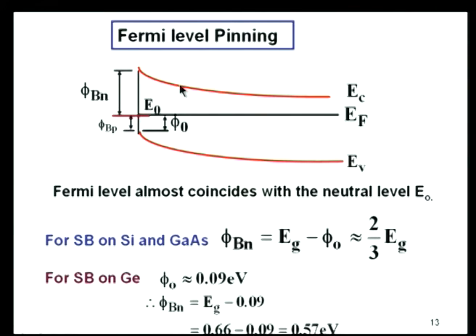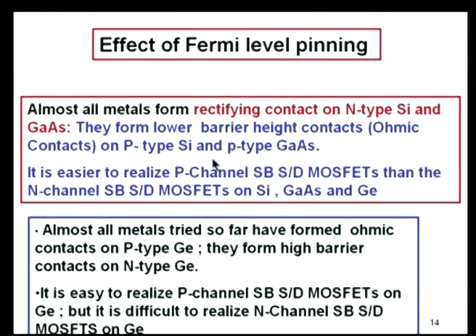So, rectifying: whenever you put a metal on these semiconductors, it will make a rectifying contact. So, it is very easy to make Schottky barrier diodes on n type materials, and it is very difficult to make ohmic contacts there. So, the effect of Fermi level pinning: almost all metals form rectifying contact on n type silicon and gallium arsenide, and also on germanium. They form lower barrier height contacts, that is ohmic contact, on p type silicon and p type gallium arsenide.